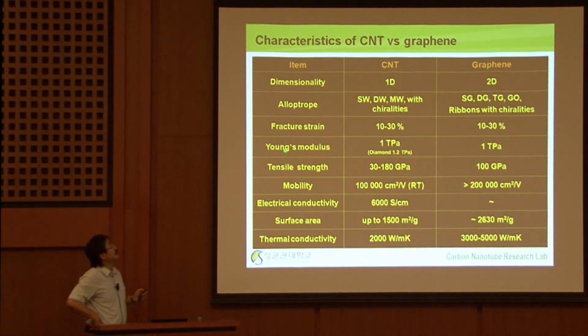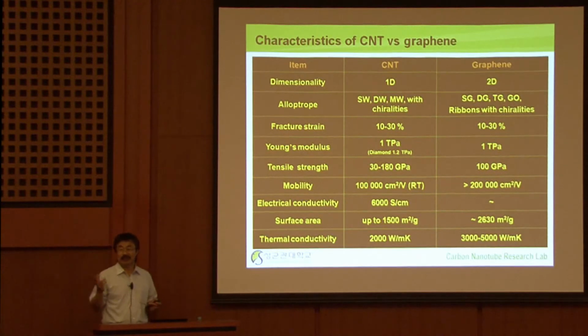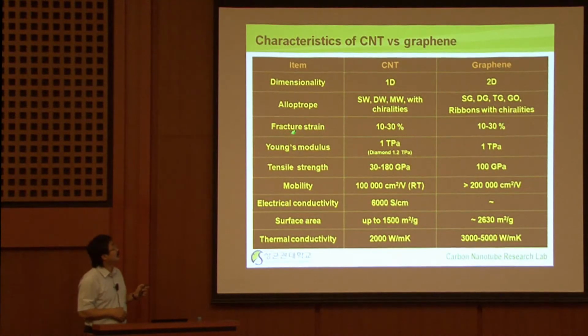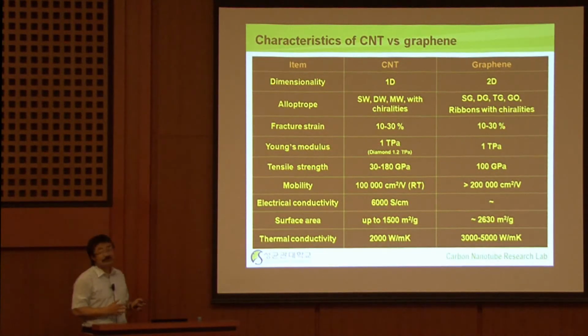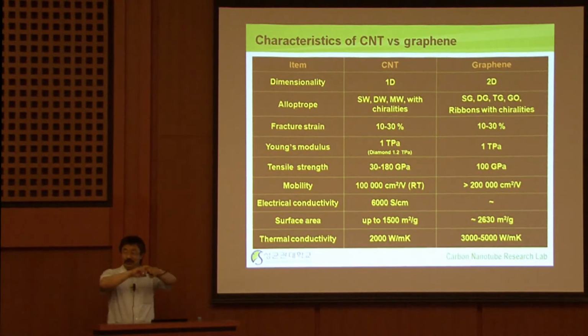If you look at the basic properties of these two materials, for instance the different types of structure, we can synthesize single-wall, double-wall, and even multi-wall carbon nanotubes. We can also prepare single-layer, double-layer, and triple-layer graphene, very similar. The fracture strain, Young's modulus, and other mechanical properties are very similar between these two structures. If you look at these numbers, the performances of the two structures are very similar, because basically it's carbon. One is simply a rolled structure, the other a flat structure, so there is almost no difference. But of course, practically there is a difference, because in some cases graphene is easier to apply or use than carbon nanotubes, and vice versa.